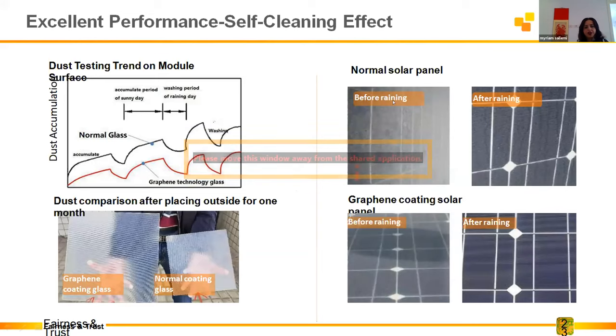Here, before raining, you can see the dust testing trend on the module surface. It's a normal solar panel before raining and after raining. So here you can see the difference. Using the graphene coating may also give us excellent performance in photocatalytic degradation reaction. Here we can find both normal ARC glass and graphene coating glass. With the organic solution, less color difference here, more color difference here. So you can see the difference.